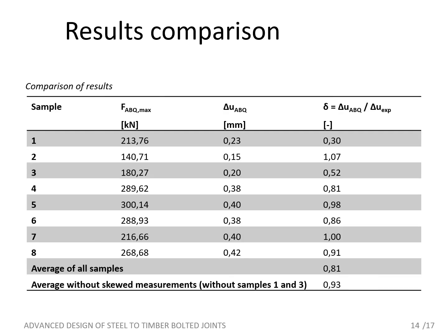The validation of all 8 samples is numerically expressed in this table, where the data on the relative displacement of measured points 1 and 2 according to the numerical model, and the ratio of the displacement between the numerical model and the experiment. The most significant result is the average value of the agreement. The deviation is only 19%, and that is really good, because when taken into consideration that for timber a deviation of up to 30% is considered as acceptable.